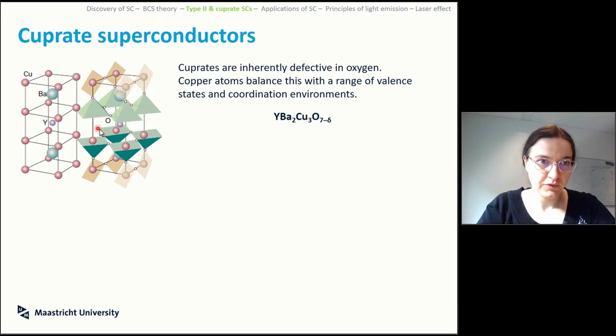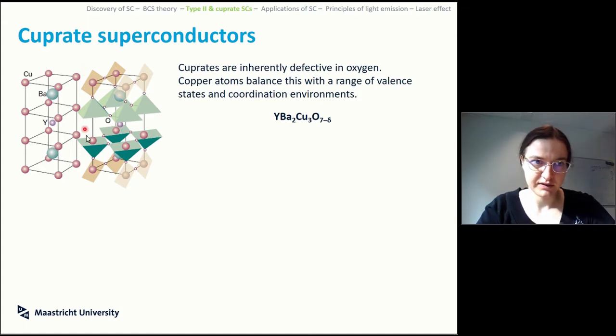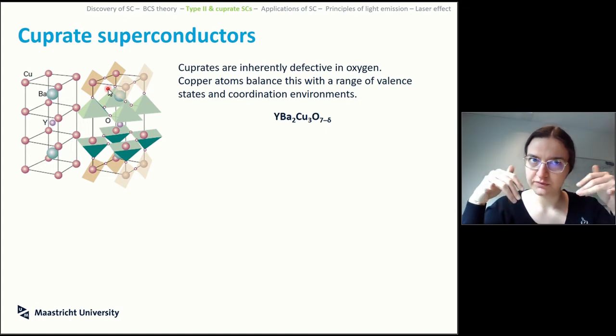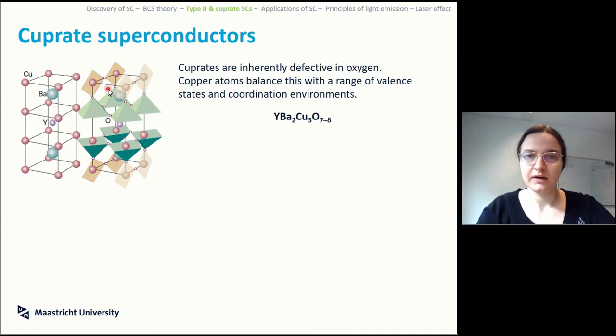So this thing should be fully octahedral, and instead you will find yourself with something that looks more like a square pyramid or a square planar arrangement. So you can either find yourself with square pyramid units on the xy plane. So if this is C, this is x, this is y, you have the planes of the pyramid in the xy plane. And instead you have square planar units parallel to the y. These units are linked by the corners, as are these units, but these are the corners of the planes, and these ones are just the corner of a square planar coordination.